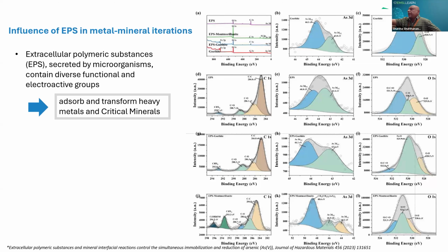If you look at the EPS, you can see again there are 2 peaks. But in this case, we have more 3+ compared to the 5+. So the EPS functional group is giving more electrons to the arsenic 5, and it is reducing the arsenic to 3+.